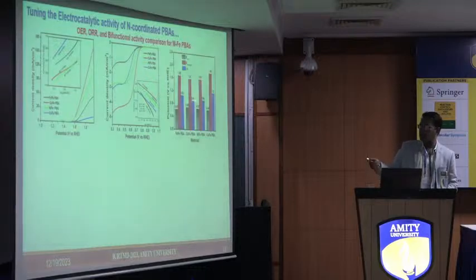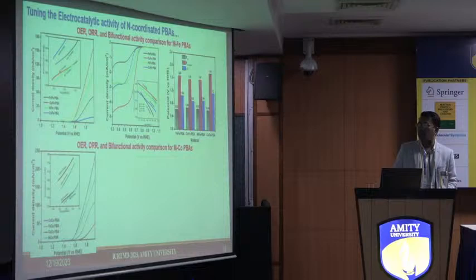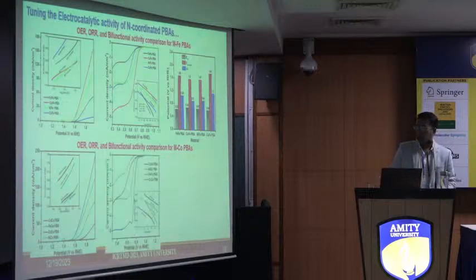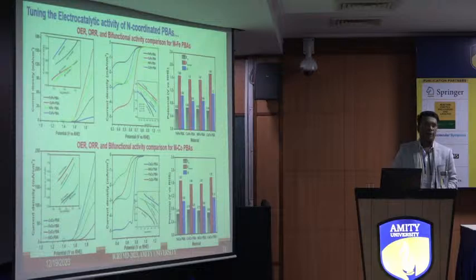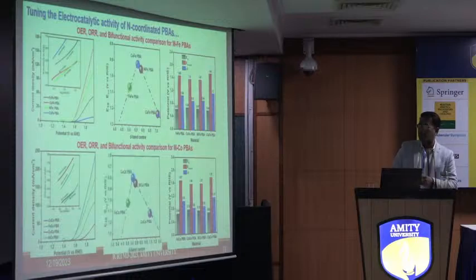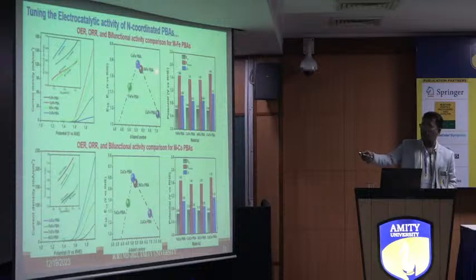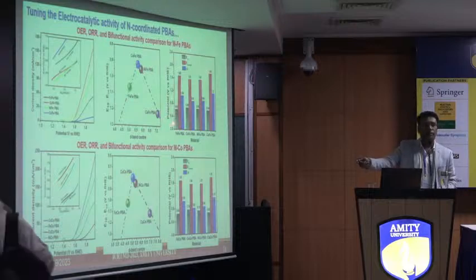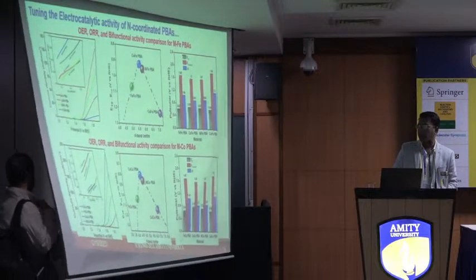And these are just the numbers to show you, to compare this. A similar trend we observed if I change the cobalt. What we observed is similar trends where now cobalt PBA shows the highest activity in both oxygen reduction and oxygen evolution reaction. Now, having said that, what is the reason why these materials are showing this? Well, by the way, this is the trend. The CoFe PBA is showing the highest activity. Fe PBA is showing very low activity. Copper Fe PBA is also showing low activity.